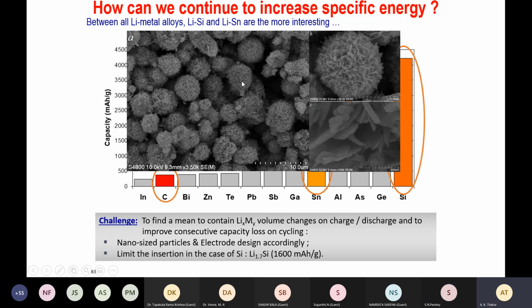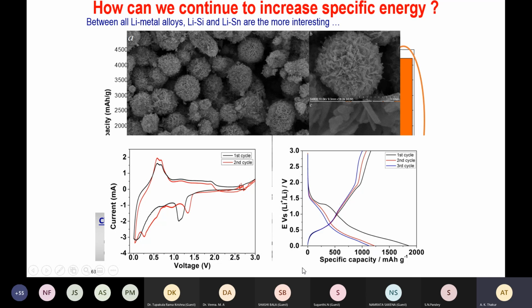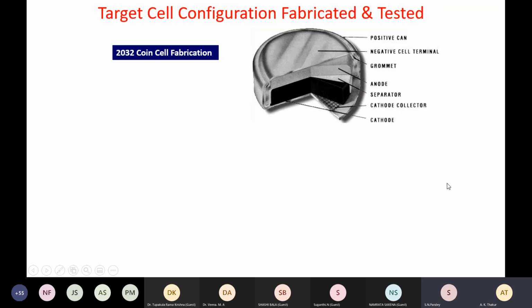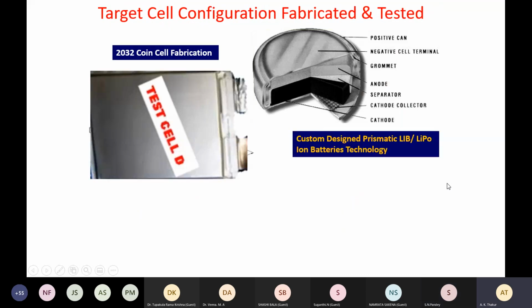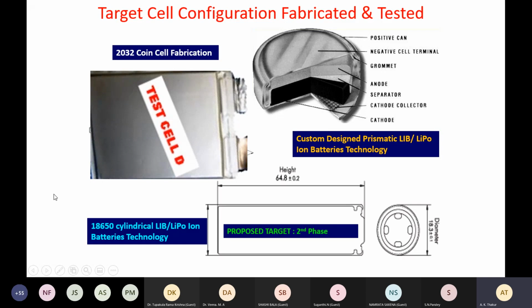Here we have developed a nanocrystalline powder material in our laboratory to address high capacity. And if we look, we have been able to obtain capacity as high as 1000 milliampere hour per gram with a specific electrode developed at our end. And when a coin cell or prismatic cell was fabricated using this, these were the fabricated prismatic cells in our labs.